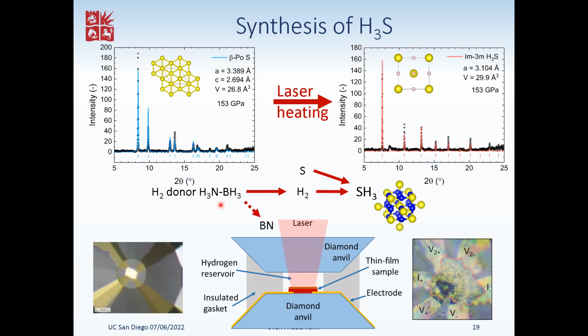The idea is that once we heat this at high pressures, we can release hydrogen and make it react with our sulfur to form hydrogen sulfide. The heating is done with a laser. We focus a laser of about 20-30 watts onto our sample. We usually heat only for less than a second because we don't want to heat up the whole pressure cell. Heating up the whole pressure cell makes the material softer, and the diamonds start to indent into the cell body, and they then start to tilt, and we've had several diamonds explode because of the heating. So one has to be careful with that.